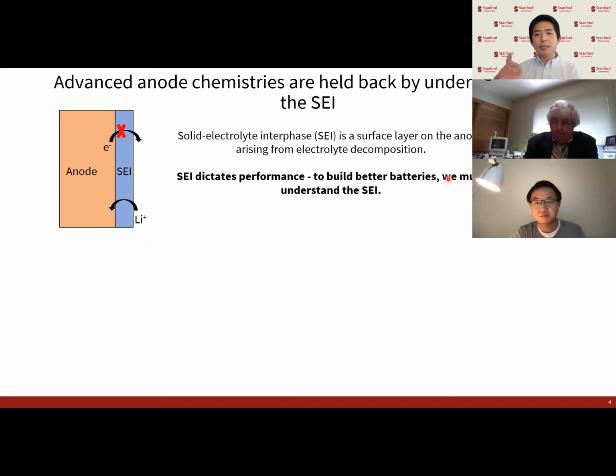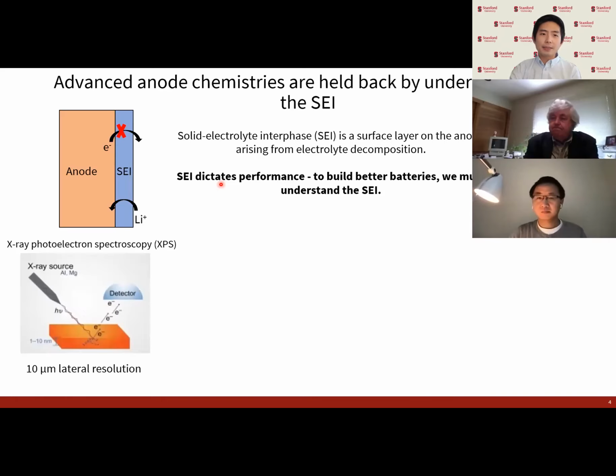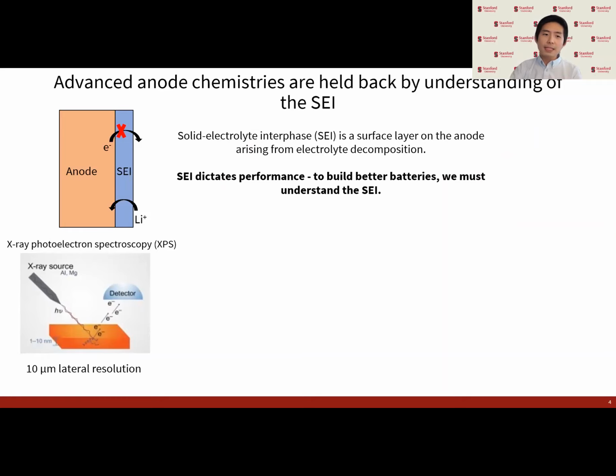This SEI is extremely important because it dictates the stability of the anode and the whole battery itself, but it also mediates ion transfer between the electrolyte and into the anode material while blocking further electron transfer. Many scientists in our field have spent significant effort in trying to characterize and understand the SEI in order to build better batteries. People typically think of the SEI as a sort of surface film on the anode. So surface analytical techniques such as X-ray photoelectron spectroscopy, or XPS, have been the go-to characterization method in the field. XPS has very good spectral resolution, but very poor spatial resolution.